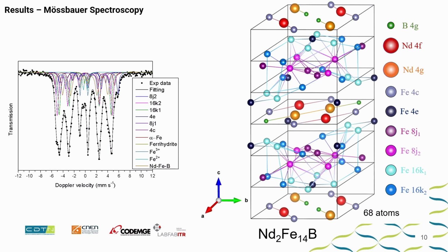We actually don't show that here. We tried to, because we extract this powder in the machine. There is a broad distribution of grain sizes, and maybe there is an effect. And with this cut machine, we don't have, like I said, a narrow distribution of grain size. We have a broad grain size.